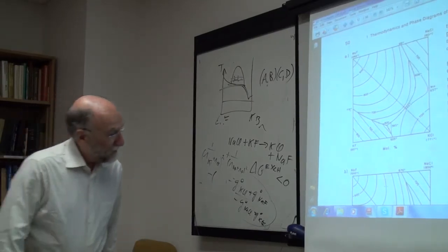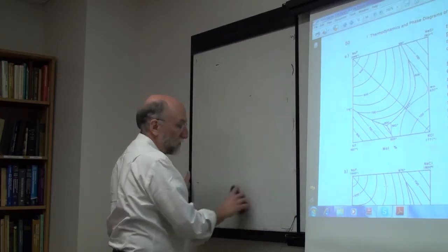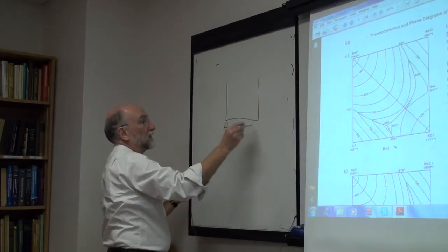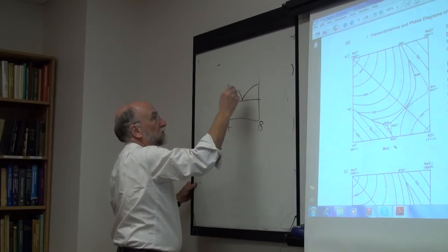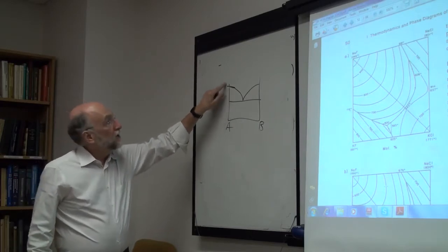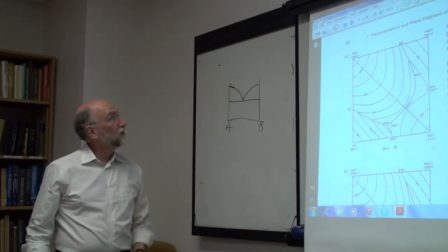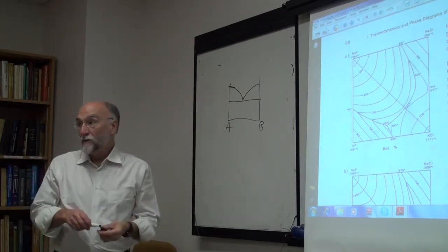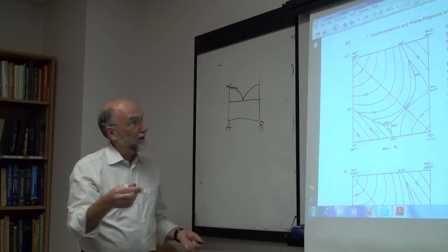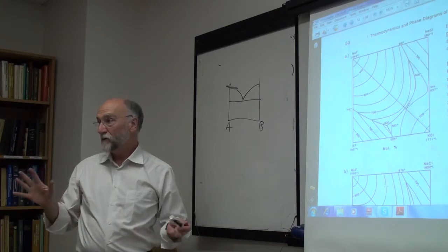The other thing that's different, this actually was taken as some of the initial evidence for molten salts. You remember, we did this a few weeks ago, if we take a system AB, say a eutectic system, the limiting slope of the liquidus is here if you have no solid solubility. Since in the limit the excess terms become very small, it's only the ideal terms that matter, and Raoult's law applies. So the limiting slope just gives you what you can use to calculate the heat of fusion. It depends only on the ideal terms. You all remember what I'm talking about?